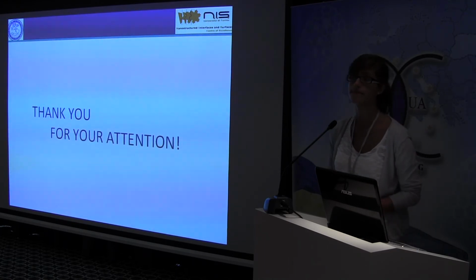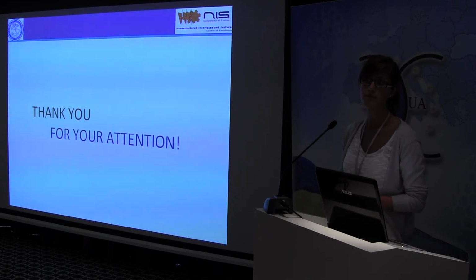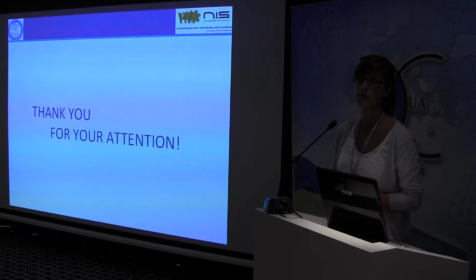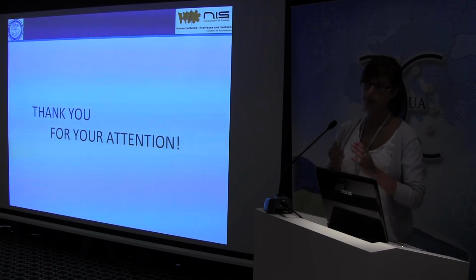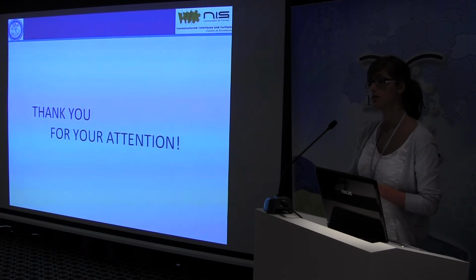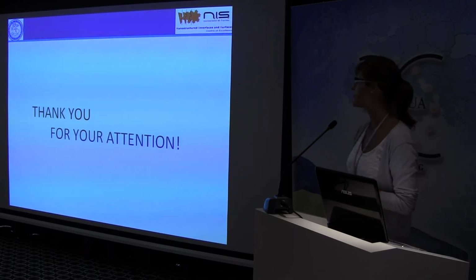Thank you for the nice report. The question is, if you add a very big amount of carbon nanotubes, like maybe 20%, I did not understand why you say that only carbon nanotubes did not give you some conductivity. It means that there is no percolation between tubes? Okay, because we use both carbon nanotubes and graphite nanoplatelets. But if you use only carbon nanotubes at a huge concentration, will you obtain some conductivity?